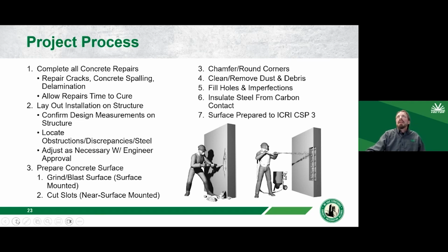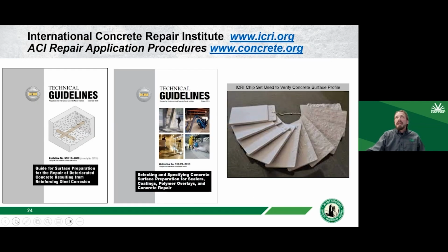An important thing to note here is we need to make sure that the concrete is cleaned and prepared and has a concrete surface profile, CSP, of 3. ICRI, the International Concrete Repair Institute, provides some really good guidance with that. As you see on the right here, we have the ICRI chip set. So in the field, you can bring your chip set with you and say, here we need a CSP 3 or 4. This is the texture of that concrete, and we can compare it to what the technicians have done during their surface prep.